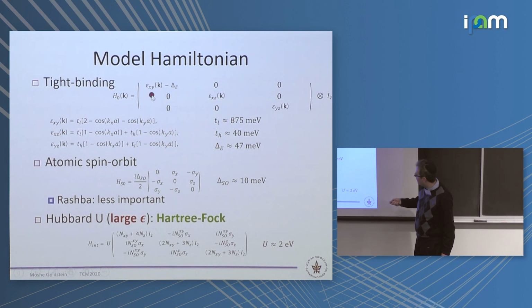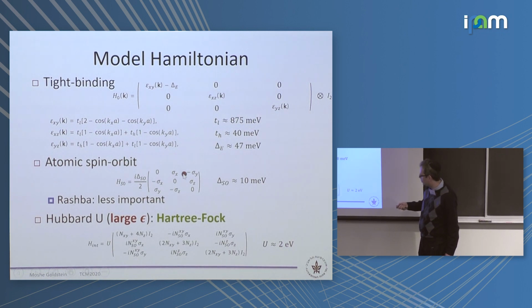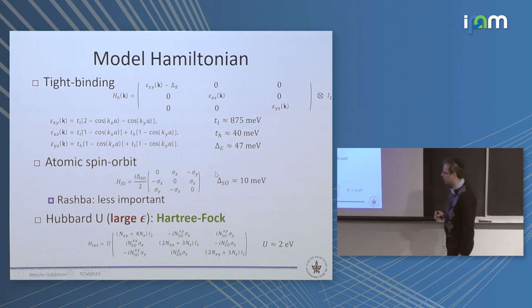Because of the confinement, the xy is going to be lower in energy. And on top of that, we need to add atomic spin orbit. This is actually very important for mixing and splitting of the bands. There is also Rashba, but it turns out to be quantitatively less important, but we can take it into account.